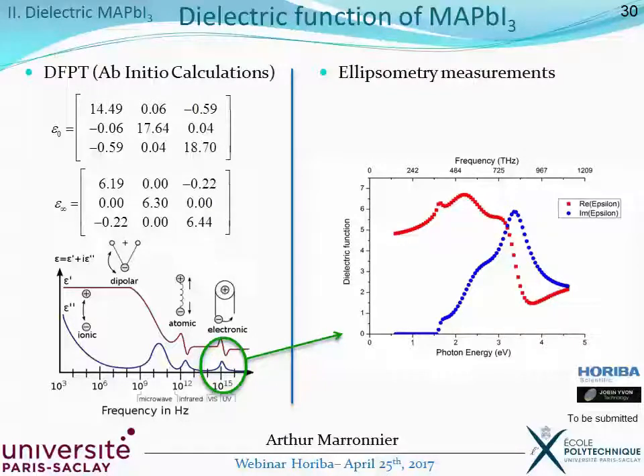You can see the transition. You have the real part in red and the imaginary part of epsilon in blue. If you look at the real part, you see that the values around 6, 7 are coherent with the values that we found from our calculations, around 6 for epsilon infinity. If you look at the imaginary part, which means the absorption, then you can read the band gap. Here, you see that you have a band gap of around 1.5, 1.55 eV, which corresponds perfectly to the theory.